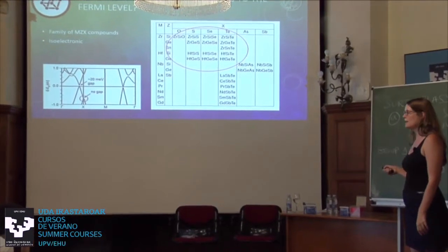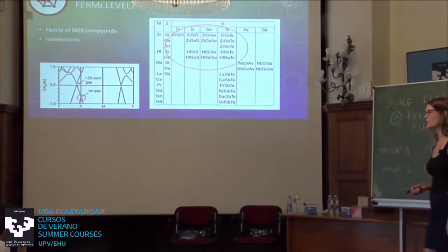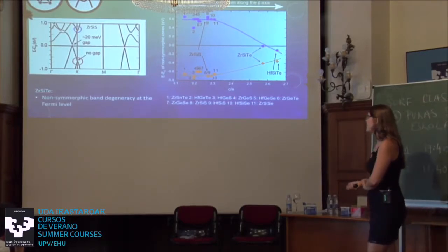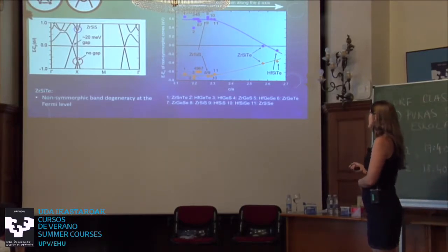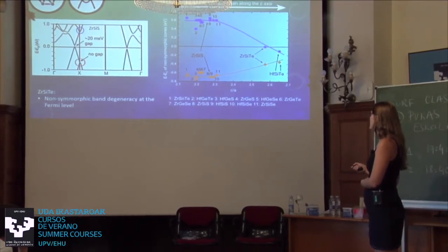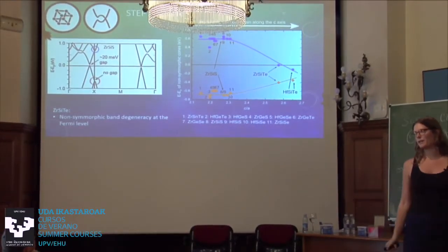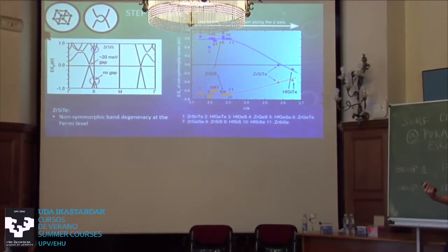These are different sizes, and therefore we can play with the chemical pressure. First, we did that in theory. So we calculated the band structures of all those materials, and we looked at the energies of the Dirac crossings, and we looked at the C to A ratio of the compounds. These are tetragonal materials, so they have a larger C axis than an A axis.